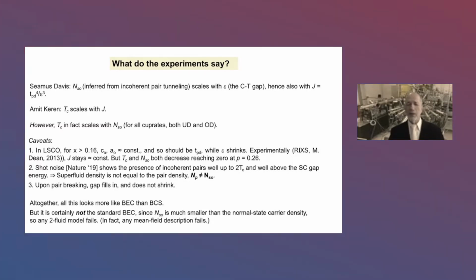Experimentally, a better way to measure J is to look at the paramagnon spectrum at pi over a, and that was measured by Mark Dean in LSCO films grown by LMBE. And what was found is that the spectrum actually didn't change from undoped lanthanum cuprate all the way to metallic and non-superconducting LSCO. But at the same time, both Tc and superfluid carrier density decrease, and they actually disappear. They go to zero at the critical doping on the right-hand side of the dome.